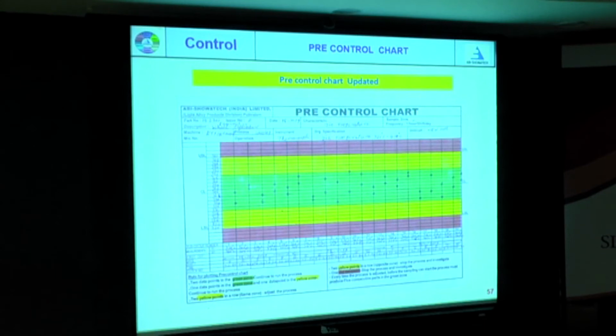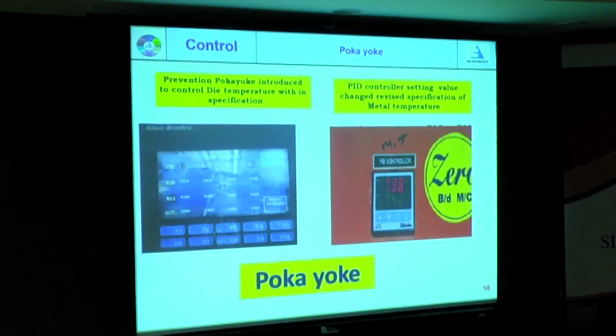We have daily monitored the die temperature, and Poka-Yoke is introduced for die temperature. We have provided a die temperature interlock with a minimum of 320 degrees and maximum of 410 degrees. This is the management of conditions. Degassing time we have visually checked, and the gas flow meter is 20 LPM, which we are reading on the flow meter. Auto closing door we have checked visually, and the metal temperature indicator is provided. Die temperature interlock is also done.